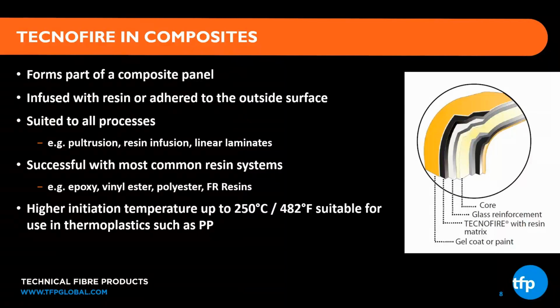Now, the gray fabric type material you saw earlier is what we call the infusible grade. So that is ready to be infused with resin. It's around 80% void of air, so it will readily accept a resin. Nonwovens are very commonly used as a breathable layer within a composite to assure a proper wet out. So they do soak up the resin. You want to keep that controlled because resins are usually a source of organic flammable material. So 30 to 40% is what we're shooting for.